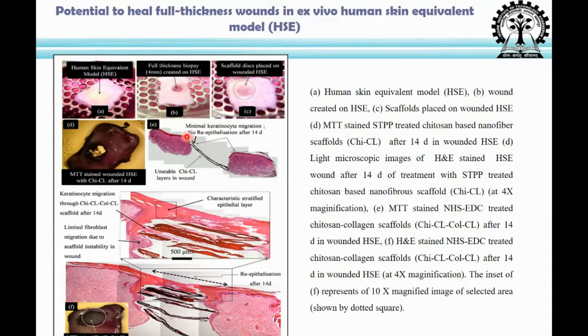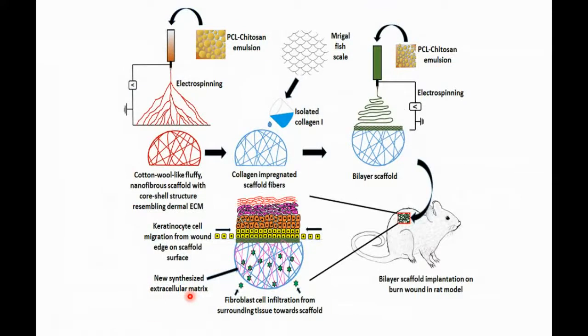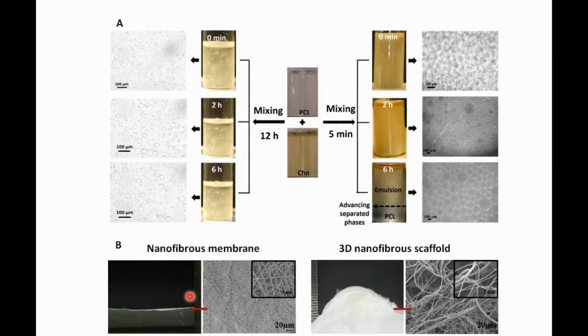As you see here, without the presence of collagen, there is no keratinocyte migration, but with collagen, there is a migration of keratinocyte. So it shows that if you have collagen with a bilayer structure, it is giving us better recovery of wounds as compared to without collagen. Similarly, we have taken another idea where we do electrospinning to make nanofibers, but we make an emulsion, and this emulsion can be used for controlling the pore size. For example, if we mix the emulsion for 12 hours and then do the electrospinning, we get the membrane. And if you mix for 5 minutes and then do electrospinning, we get a fluffy mass, because here the droplet size is much bigger.